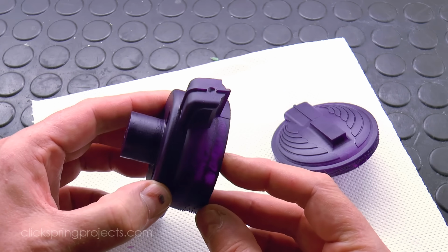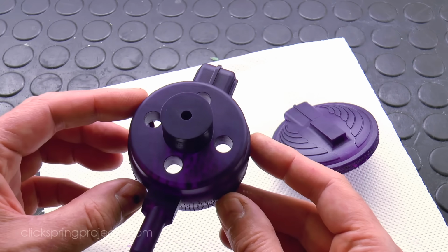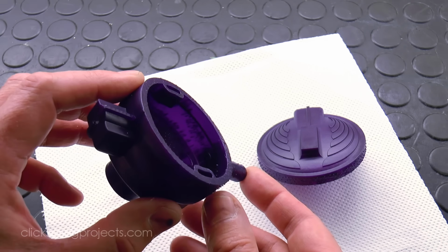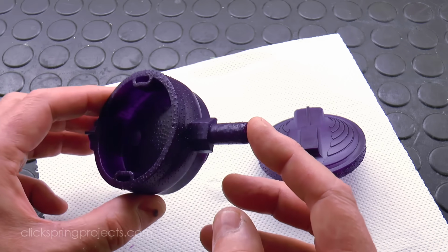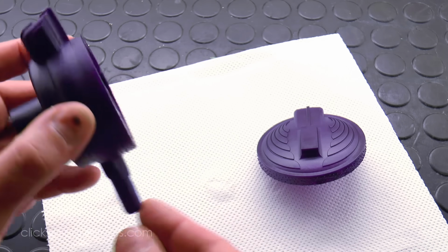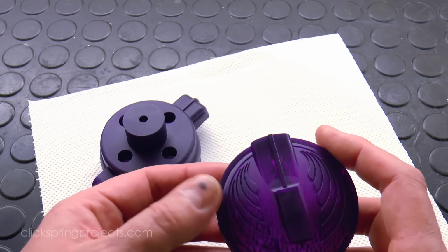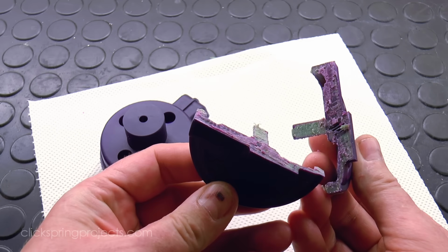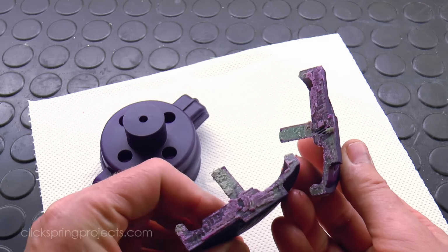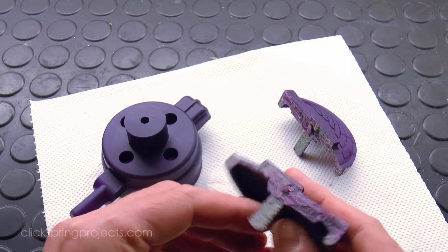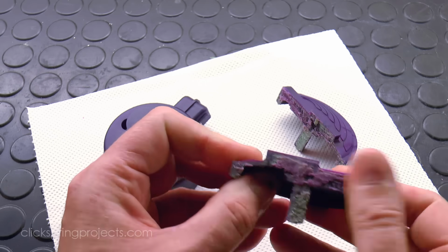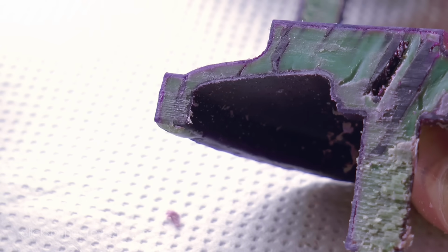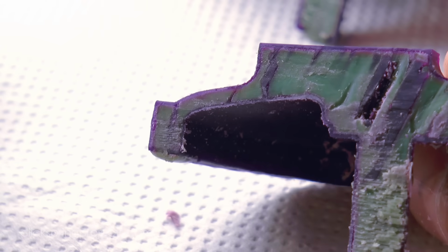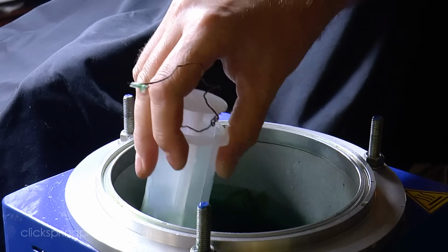But an additional step to help solve this is to print the models hollow, with the thinnest possible wall thickness that'll still permit the object to hold its shape, and then to fill it with wax. This maintains the rigidity of the pattern for handling, while helping to solve the cracking issue. The de-wax sequence is arranged so that the wax is melted from the mould before resin burnout, allowing an internal cavity to form. This gives room for the printed resin to pull back from the investment surface as it breaks down, with less risk of it damaging the mould face as it does so.